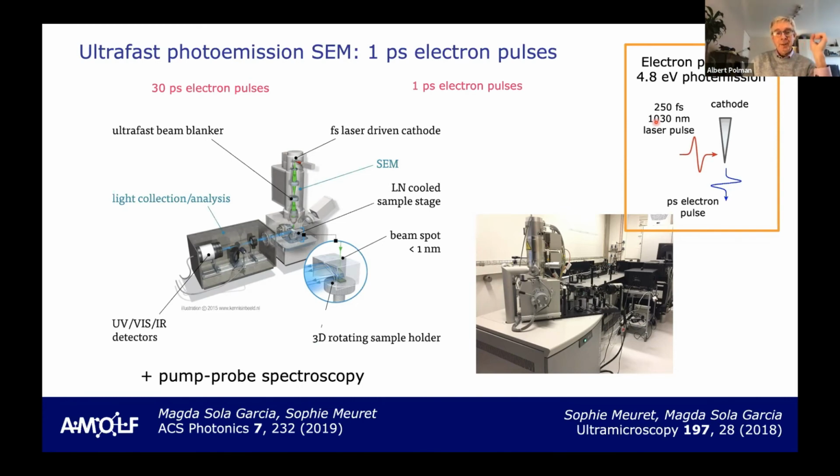And I don't have the time today to show data on this, but we just published the first paper on this nanoscale spectroscopy, where we also do pump probe spectroscopy. It means the laser drives the tip here and then creates pulses, but the laser also goes into the sample and optically excites it. And then we can vary the time delay between the two and pump with the laser and read out with the electron beam or vice versa. And that's all just working now.